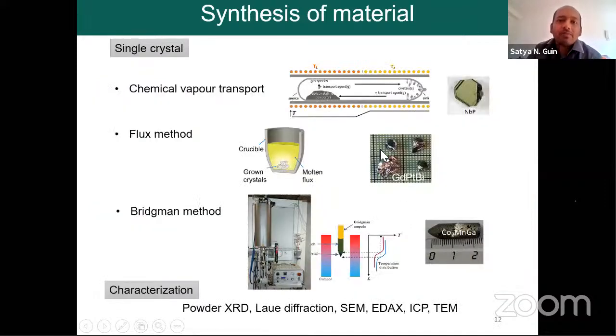You can also do different kinds of single crystal synthesis. For example, chemical vapor transport synthesis, where you use polycrystalline powder to grow single crystals using a temperature gradient in the furnace. With the flux method, you use a molten flux for the growth of high quality single crystals. The Bridgman method is generally used for the growth of very high quality, large single crystals. After growing polycrystals and single crystals, you can do different characterizations like powder X-ray, Laue diffraction, SEM, EDAX, ICP, and TEM.